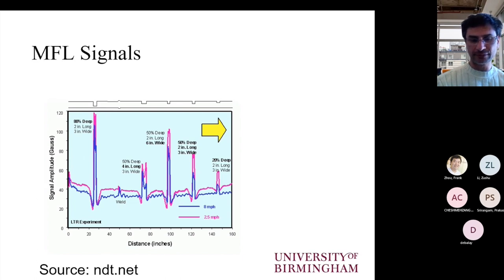So the purple trace is the inspection carried out at 2.5 miles per hour, and the blue trace is at 8 miles per hour. So here you can see that the response for the higher speed inspection is somewhat reduced, even though the defects are mostly detectable in both cases. But the amplitude of the response is lower in the second case, and this is because of the eddy current effects, which are caused by the fact that the probe is moving faster along the component that we are inspecting.